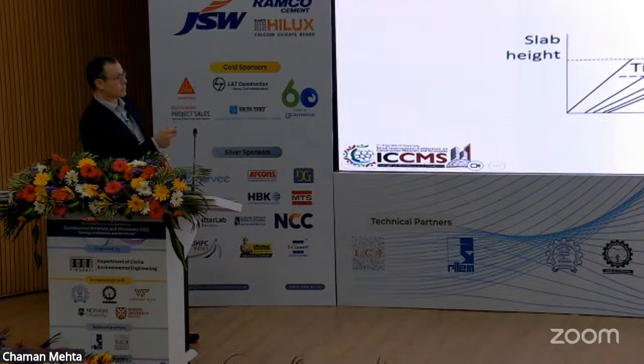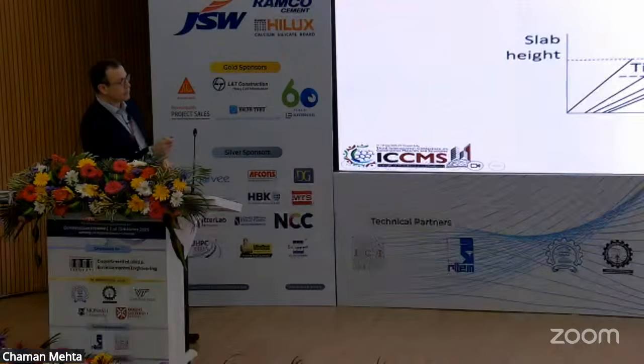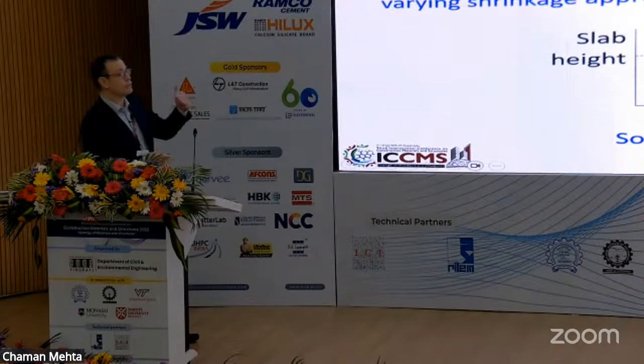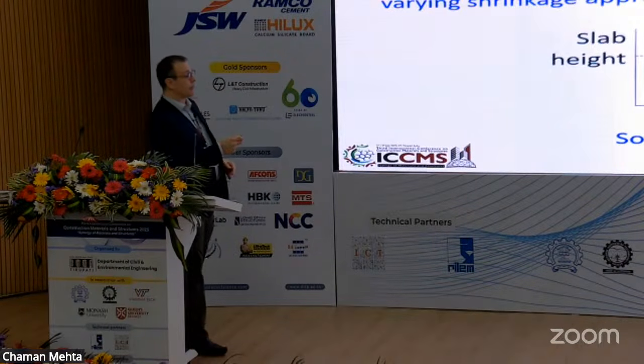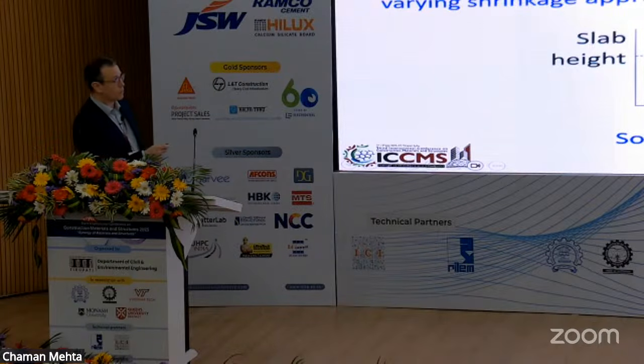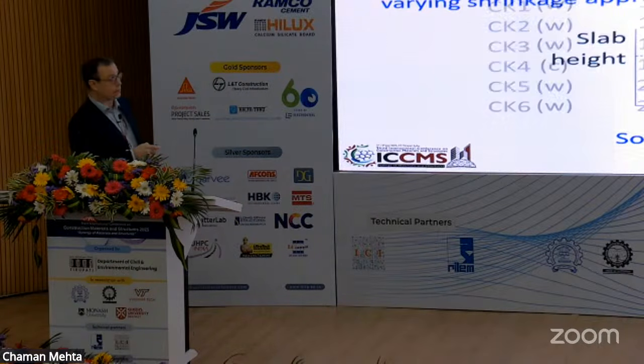And when you have the sheeting at the bottom, so it's sealed, and when you do this test you just put some plastic to seal it, you create a different gradient, which is the cause of the additional deflection that you saw before. So in reality, we confirm that what you do in reinforced concrete design is fine, but when you go into composite slabs, you need to move to a shrinkage gradient.